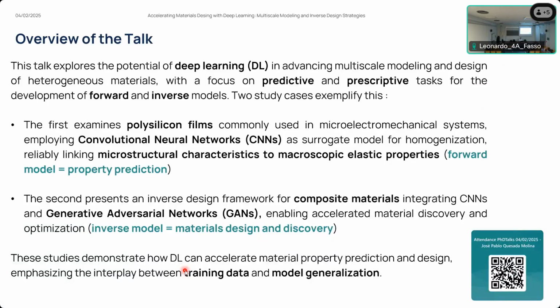And in this case, we will use convolutional neural networks to provide a surrogate model for homogenization in such a way that we can reliably link the microstructural characteristics of these materials to the macroscopic elastic properties. In the second study case, instead, we will present an inverse design framework for composite materials with periodic microstructures. And in this framework, we will integrate the convolutional neural network as a predictor module, and we will also integrate generative adversarial neural networks as the generative model in order to achieve targeting of materials with a specific combination of properties, accelerating the material discovery and optimization process.